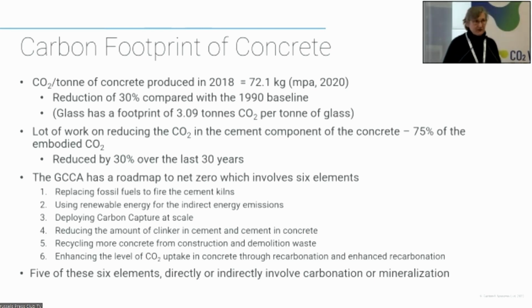About 60% of the CO2 in cement is the direct result of calcination of the limestone. So you have to heat limestone up, and that releases the CO2 to get your cement chemistry right. So if you can reduce the amount of that sort of Portland cement type clinker in the cement, you can lower the overall footprint of the cement.